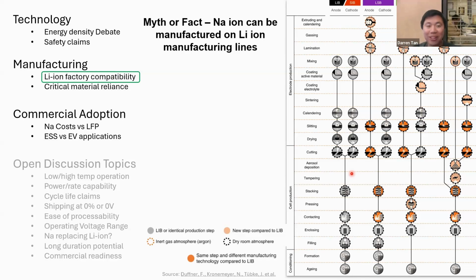Now, I want to address the depends part. There's one caveat that is often not reflected, which is that a lot of sodium-ion battery materials are far more moisture sensitive than lithium-ion battery materials like LFP. Although LFP battery lines have a certain dew point control in dry process, certain ppm levels of moisture control in the slurries and many other aspects, sodium-ion batteries may need to be stricter. That's one aspect of why it cannot be immediately transferred unless certain upgrades or compliance is ensured. Another aspect is also the concept of throughput.